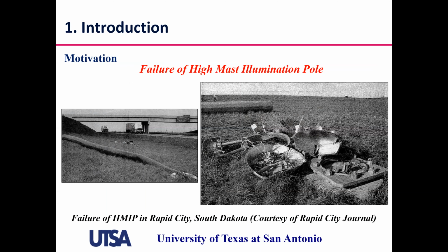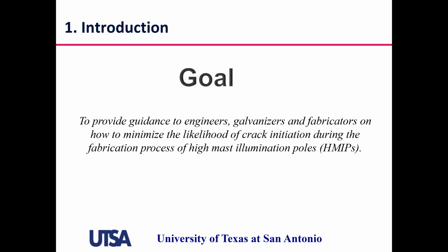Now, if these small cracks go undetected, because they are exposed to fatigue loading from winds while they're in service, they can actually propagate and the poles can fail and cause a catastrophic failure that can even cause some loss of human lives. So it's very important that we try to minimize the formation of these cracks. So we're trying through our study to provide some guidance to engineers, galvanizers, and fabricators on how to minimize the likelihood of crack initiation during the fabrication process of high mast illumination poles.